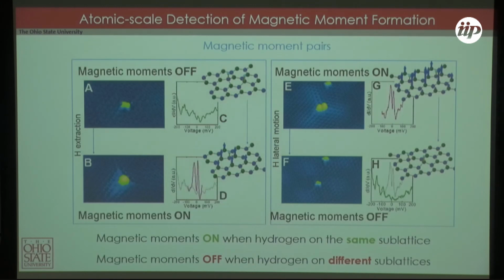And then you could do even a little bit more. You can take two of these and position them. And what's nice is, you can't maybe see it here, but there's this triangular shape. So depending on if you're on the same sublattice or the opposite sublattice, these three lines will come out in the opposite three directions if you're on the other sublattice. So you kind of know where you are.